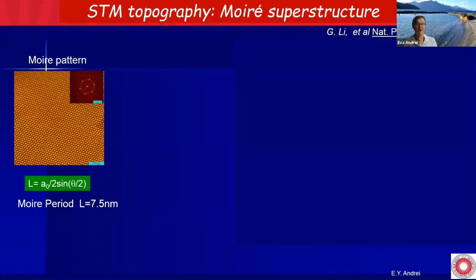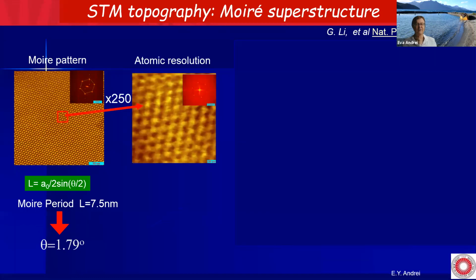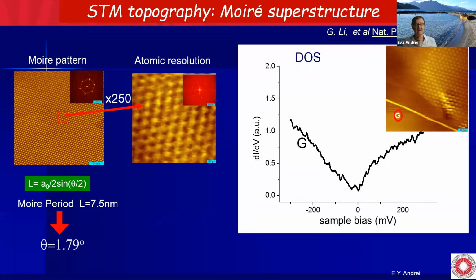And that was these Moiré patterns. Here, for example, the period is 7.5 nanometers, which corresponds to an angle of about 1.79 degrees. This is the Fourier transform of your pattern. And if you zoom into atomic resolution and compare the Fourier transform, you can extract the exact same angle, 1.79 degrees. And then we did the dI/dV spectrum.